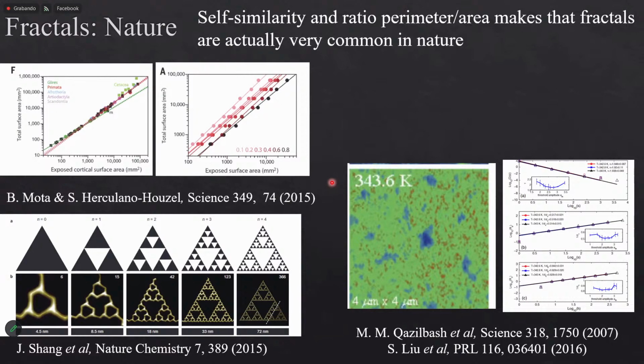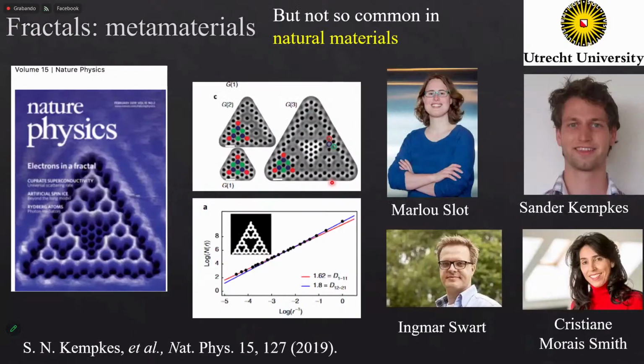And this is because, when you think about the formation of lattices, usually you have forces that are more volumetric in origin that form this kind of lattices. So in most cases, you're not going to see these fractals, and also they're not a crystal, right? So you're not going to see them forming naturally. And this being the case, the group in Utrecht, led by Professor Cristiane and Professor Ingmar, where the design was done by Sander and the experiments by Marlou, was actually able to build this fractal lattice and show that you can have a tight-binding model in fractals.